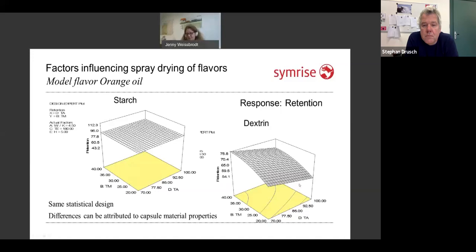But in this case, you see an opposite effect concerning the outlet air temperature. An increase in outlet air temperature leads to a drop in the retention. So what is happening here? The outlet air temperature determines the temperature of the droplet itself while it's drying. And this means the higher the temperature, the higher the kinetic energy. And this means that the movement, the turbulence within your droplets, will be higher at higher temperatures. So your active is constantly transported to the surface and will get lost if you have a higher temperature. And this effect can be seen here.